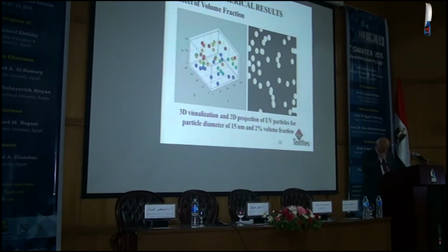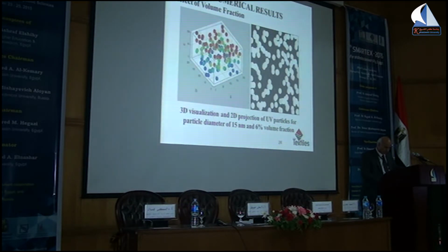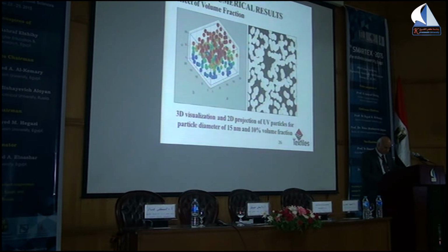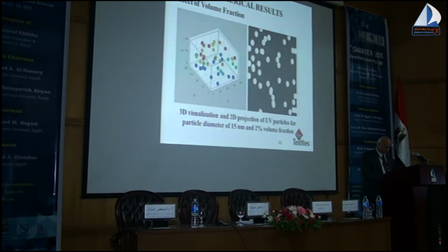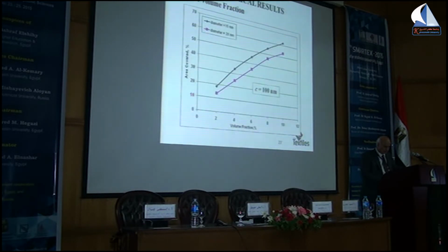Effect of volume fraction. We played with the volume fraction, which means more particles. We add more particles, and then if you have 10%, we change it from 2% to 10%. You can see here, and this is a summary of the results. We are looking at the area covered, the projected area covered, and the volume fraction for two diameters, 15 and 20 nano.